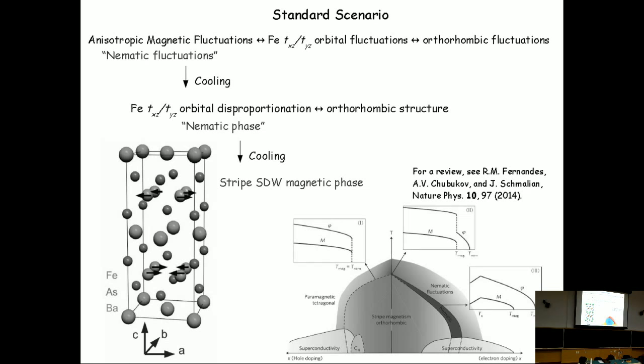For some electron doping, we start realizing that the transition temperature for the magnetic transition and the orthorhombic transition temperature are not exactly the same. So they are slightly different. And then here in red, you have a regime where the magnetism has already disappeared, but the structure is still orthorhombic. And then at a slightly higher temperature, the system becomes tetragonal again. And this difference between the magnetic transition temperature and the structural transition temperature starts to increase as the doping increases.